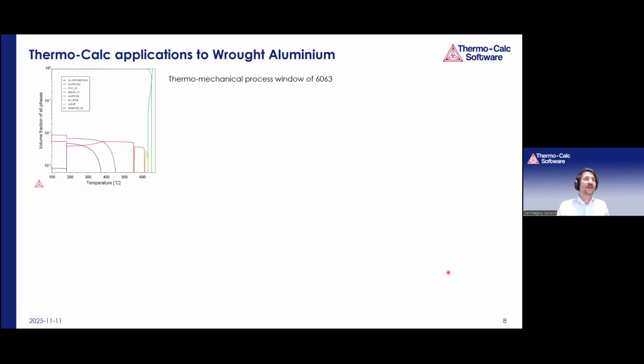Next, quick overview of applications to wrought aluminum alloys. So wrought aluminum alloys, we do thermomechanical processing, so we can identify processing windows. This example is on alloy 6063, but you can do this on any kind of alloy grade. So here we show the equilibrium phase fractions as a function of temperature, representing the microstructure. You will have different temperatures, so you can identify some temperature limits. For example, here the solvus temperature for the formation of Mg2Si, which is a problematic intermetallic compound. So this will set a lower temperature limit for a processing window.